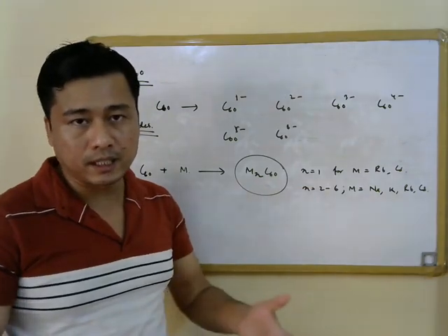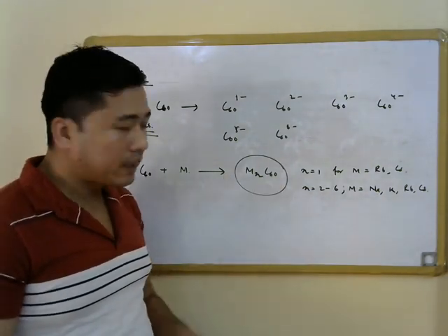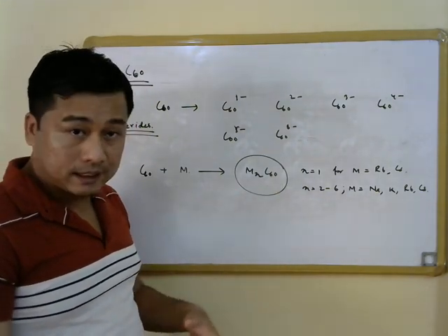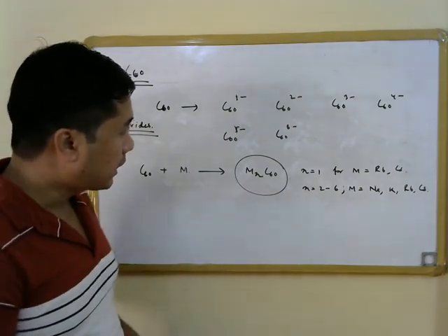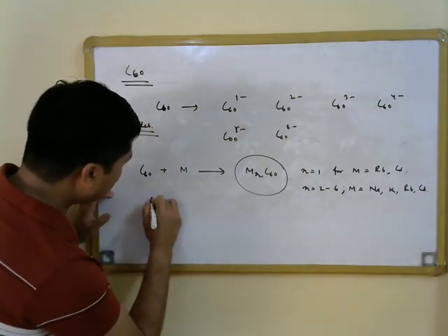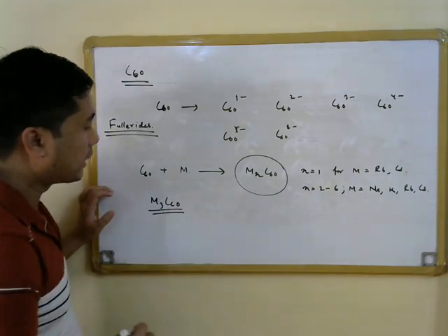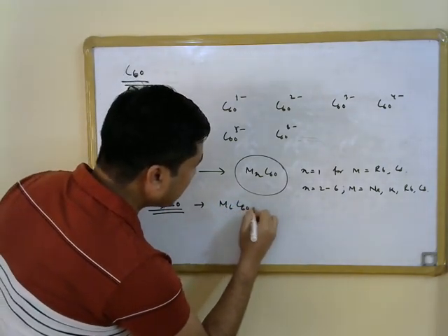These molecules have very interesting characteristics. Unlike C60, these molecules are very good conductors, and especially the conductivity is highest for M3C60, while M6C60 is an insulator.